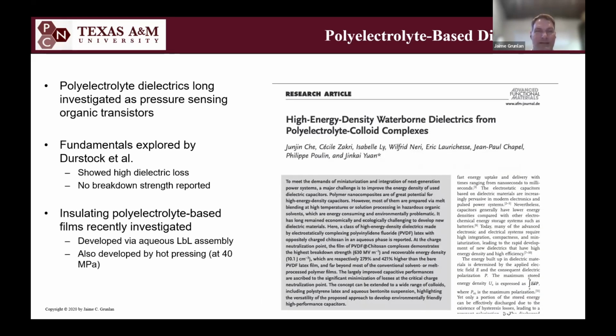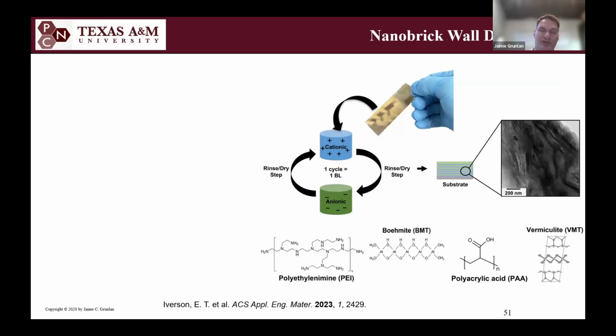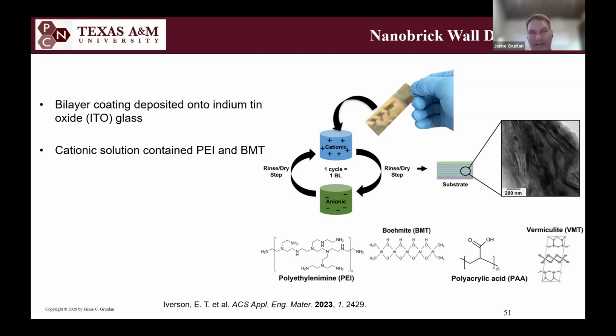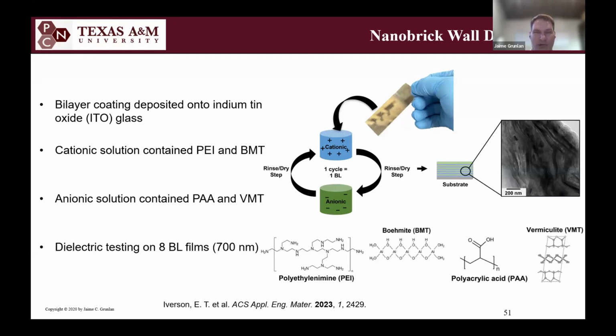properties, I think. And so I'm going to just show you one example where we took polyethylenimine and we stabilized boehmite clay. That's alumina, Al2O3. It's a platelet like a clay, but it's boehmite. And then vermiculite is an aluminosilicate, a typical clay. That's usually a little bit anionic, but we further stabilized it with polyacrylic acid. And so we had this cationic and anionic solution, but the major component was a clay in each solution. So we were doing layer by layer with two different clay or platelet materials. So it was a unique kind of brick wall.